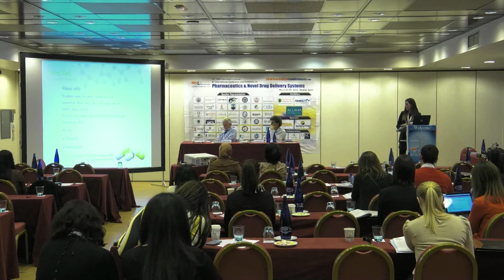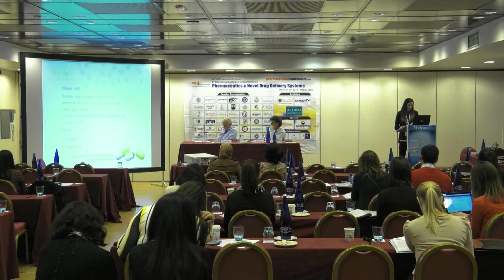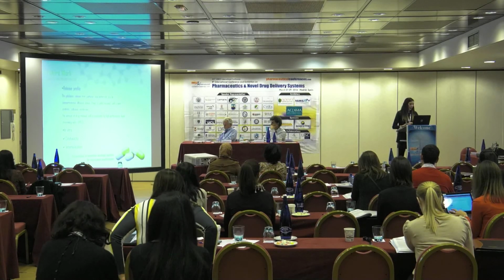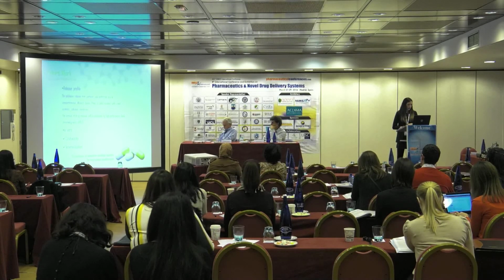And also, of course, as I told you, these were preliminary results. We want to check cytotoxicity and internalization, because another interesting thing regarding these peptides is that, opposite to the common thing that we used to chase in nanomedicine, they don't need to internalize into the cells. If they internalize, we lose the therapeutic effect. So, as I put there, the idea is to extrapolate all this to these innovative oncologic peptides.